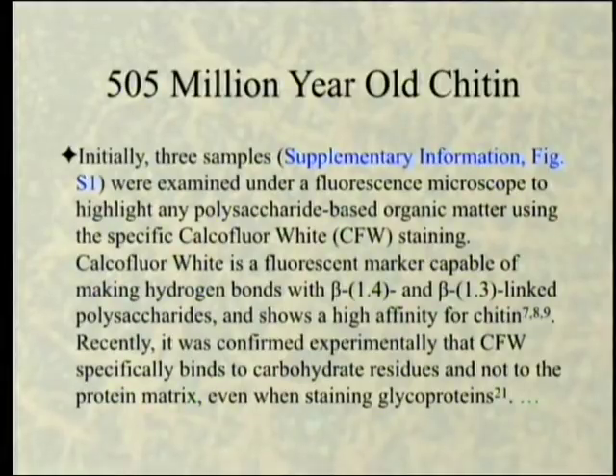Initially, three samples were examined under a fluorescence microscope to highlight any polysaccharide-based organic matter using this specific calcofluor white staining. Calcofluor white is a fluorescent biomarker capable of making hydrogen bonds with beta-1,4 and beta-1,3 linked polysaccharides, which beta-1,4 happens to be the chitin linkage, and shows a high affinity for chitin, not surprisingly. Recently, it was confirmed experimentally that CFW specifically binds to carbohydrate residues and not to the protein matrix. So they're actually getting chitin, not the protein that's around the chitin, even when staining glycoproteins.